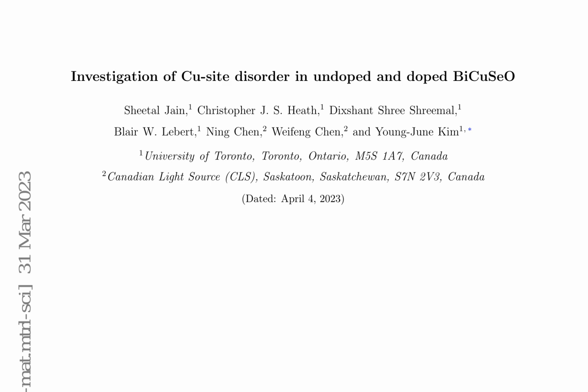The authors also present the results of Rietveld refinement of X-ray diffraction, XRD, data taken at room temperature, 298 K, for both BiCu1-xAgxSeO and Bi1-xPbxCu1-xAgxSeO samples. The lattice constants a and c of the tetragonal unit cell with space group P4/nmm, number 129, are provided in Table I. The values of a and c are found to increase slightly with increasing x in both series of samples. In the EXAFS fitting, the amplitude reduction factor S_0 squared is determined to be close to 1 for all temperatures, so it is fixed to its room temperature value for all edges in the final fits. Both the real and imaginary parts of the R-space data are fit in this analysis.